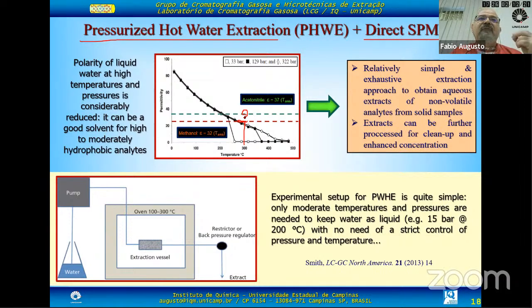So you can use very hot water, which you can obtain at very high pressure, as an extracting solvent for hydrocarbons, for example. This is relatively simple. You just have some device to keep the water as liquid at those temperatures and pressures, and use it to extract your sample. After the procedure, you have your petroleum hydrocarbons in a very clean water sample. Then you can stick your fiber inside that water extract, re-extract your hydrocarbons, and analyze them.